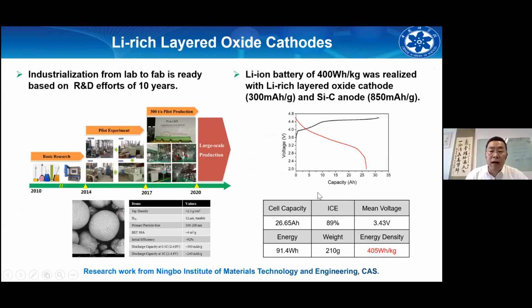Now I want to highlight some very important research I feel. Firstly, the lithium-rich cathode for high energy density lithium batteries. Lithium-rich cathode material was proposed by Thackeray and Johnson in 2001. However, there are still a lot of challenges like voltage decay, cycle life, and gas release. After long-term research and optimization, we try to scale up production of this material to develop high energy density rechargeable lithium batteries. Here is the research from the CAS Institute.